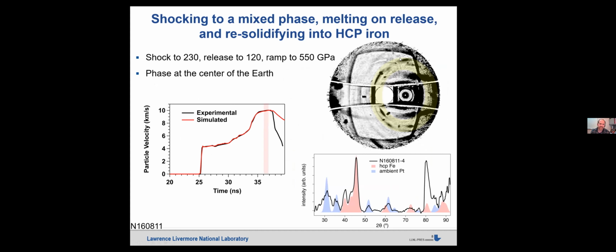And so what you're looking at is a dewarping, a stereographic projection of the image plates. And what I'm showing here, I'm highlighting in yellow, is the region over which you'll see the diffraction data from the iron. And so upon an experiment here we performed in 2016, we shocked to 230 GPa. So 230 GPa is on the mixed phase. So iron starts melting on the Hugoniot at 220 GPa. It completes melting at around 260 GPa. So we shocked to 230 GPa into a mixed phase.